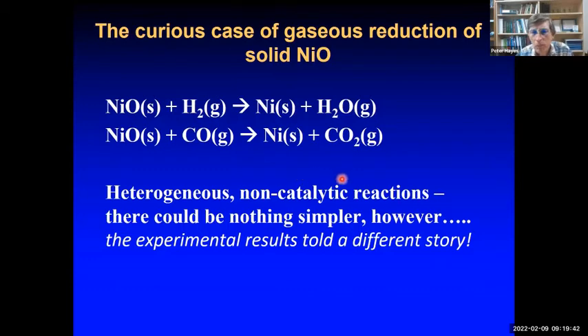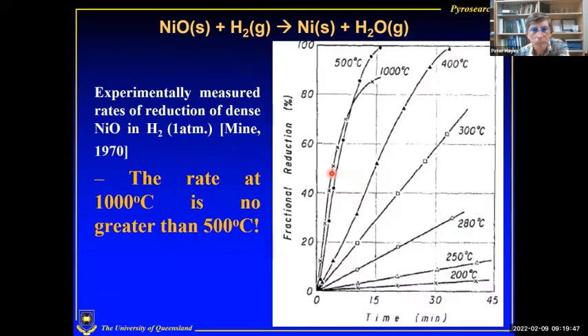So what happens when we look at this type of system in control conditions? These are some measurements of the fractional reduction as a function of time for reduction of nickel oxide in hydrogen. So these are isothermal reaction experiments. And you can see at low temperatures, the reaction rate is very low. The slope of this line is very low. Increases as we increase the temperature from 200 up to 500.